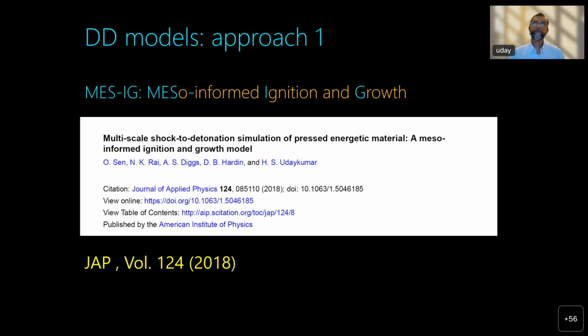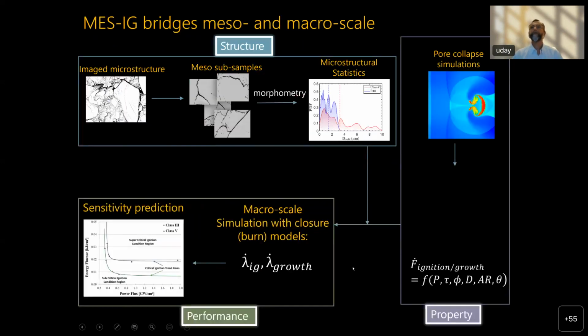So the first approach for the DD modeling is MES-IG, and this paper came out in 2018, and we've used this for many things since then. In the MES-IG approach, what we do is we bridge the scales between the meso-scale, that is the microstructure, and the macro scale to get the performance simulation. We bridge it using single pore collapse simulations. So this is important as a distinction. These single pore collapse simulations are very fast. You can do hundreds of them in a couple of days. And then you can collect the data from these single pore simulations.